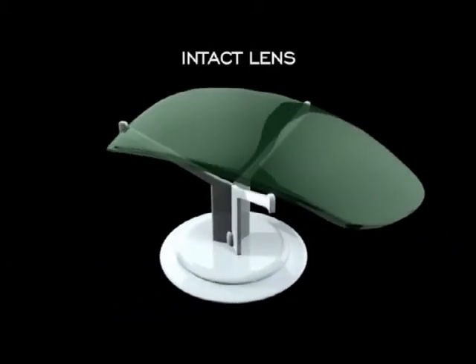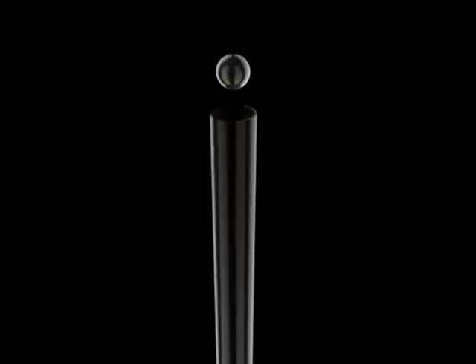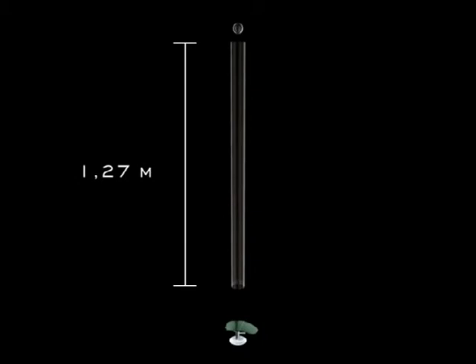Drop ball test. This test is required by US standards. This test verifies the lens resistance to even particularly violent blows. During the test, the lens is struck by a steel ball 16 mm in diameter, which is dropped from a height of 1.27 meters.